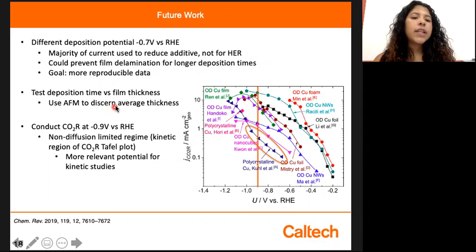To further test the relationship between deposition time and film thickness, we could take more AFM pictures to see the average thickness and height. And then to conduct kinetic studies, we could run CO2 reduction at negative 0.9 volts versus RHE, which is the kinetic region of the Tafel plot. And that concludes the end of my summer project.